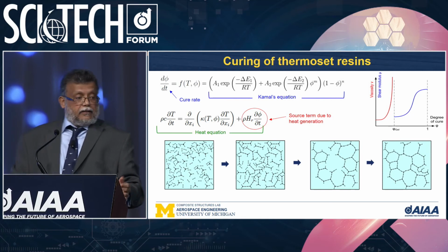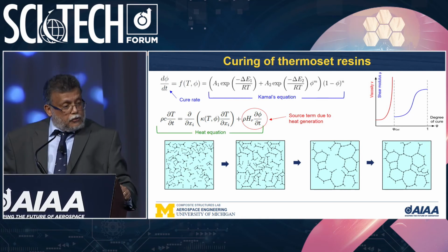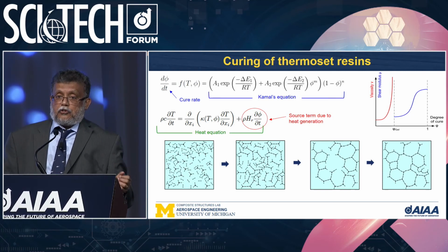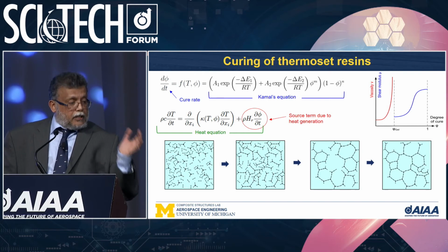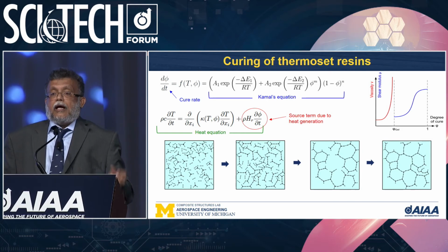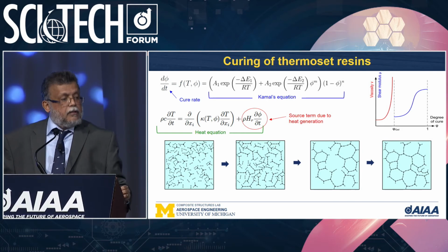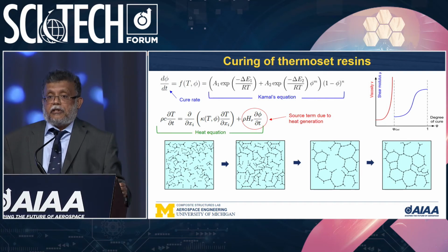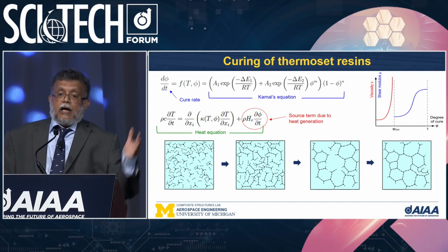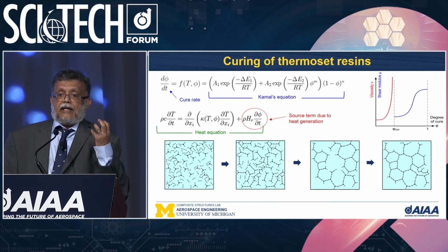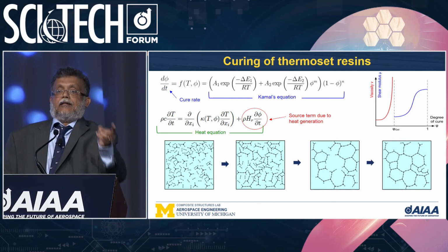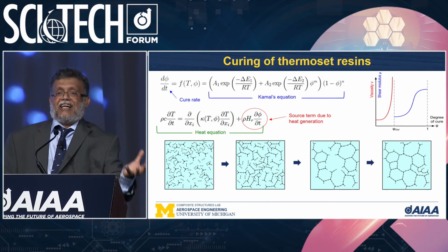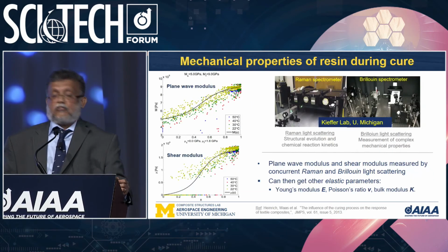So if you want to predict this, you have to go to basics. You have to look at how thermosets cure. They cure by forming networks, and this network formation is governed by what is known as Kamal's equation for the network density. As the networks increase and get solidified, you get a solid developing from a gel-like material. Unfortunately, this happens in the presence of fibers.